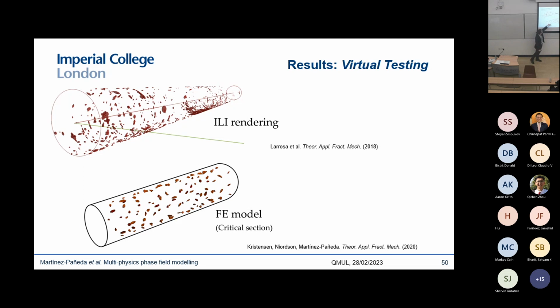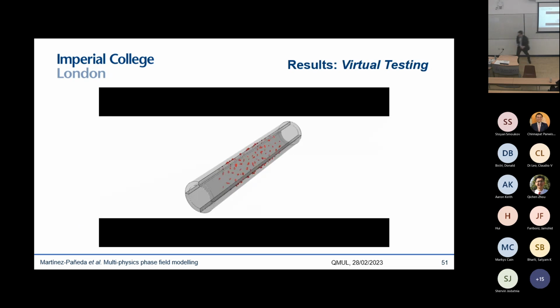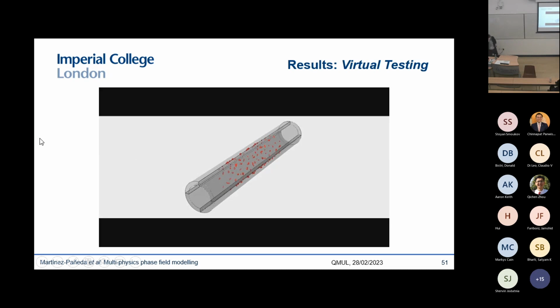And there we introduce hundreds, more than 100 of those defects. Because we're solving for the phase field as a degree of freedom, it's very easy for us to introduce those damaged regions as an initial condition. And then we can load our pipeline to in-service conditions.